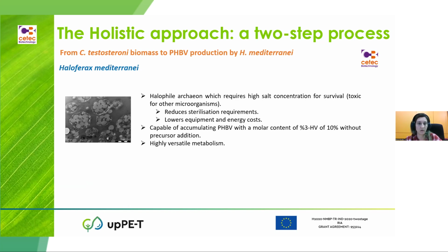This microorganism is also capable of accumulating this kind of biopolymer with a molar content of hydroxyvalerate of 10% without precursor addition, but we can also modulate and increase the hydroxyvalerate molar content, adding some volatile fatty acids to obtain a PHBV with a hydroxyvalerate content of 30% or more than 30%, as we have obtained in the upPE-T project. And it is also a microorganism with a highly versatile metabolism, which allows us to feed them with several wastes, such as organic wastes which contain nutrients to feed them, so we can replace commercial substrates with these wastes and also reduce the cost of the overall process of PHBV production.